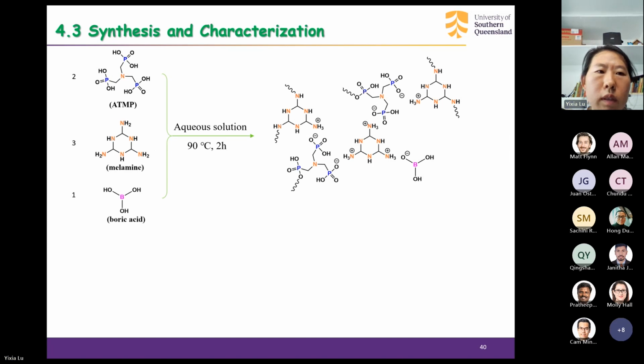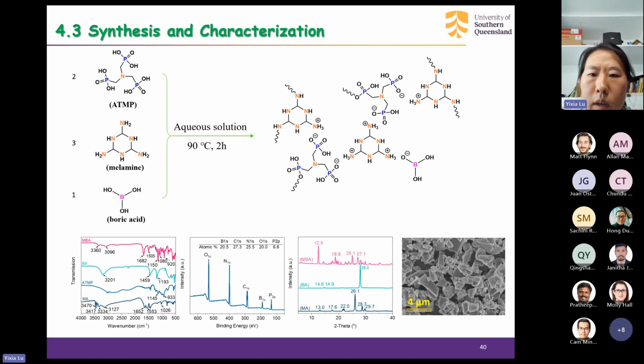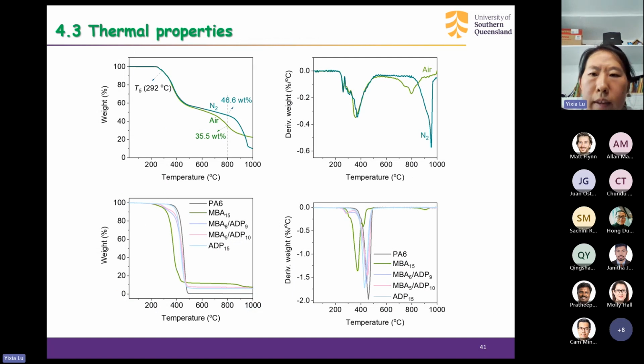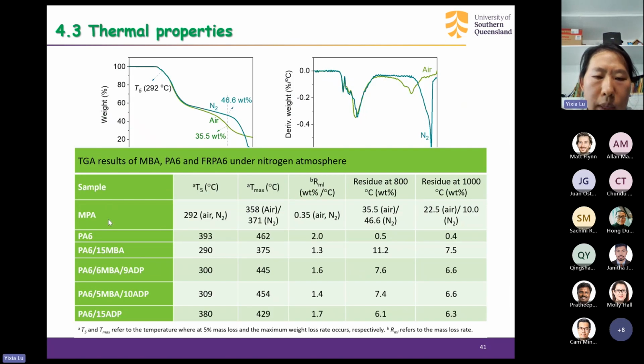We also employed melamine as the starting material. The boron element is from boric acid, and we also use ATMP as one of the starting materials. This is also reacted in aqueous solution. We characterized the product by using FTIR, XPS, XRD, and SEM. MBA. Sorry, I forgot to denote this here. And the TGA result says it is quite thermally stable. Here we can see from this table, we just add 15% as the total amount.